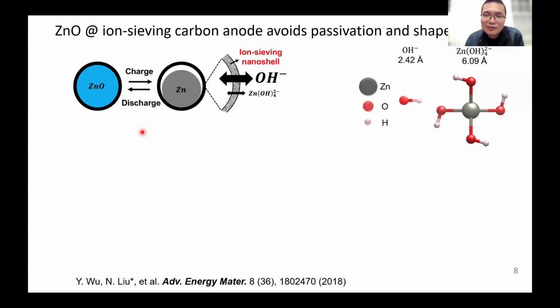Historically, people don't use this type of structure for the zinc electrode, and our approach is very innovative. We hope to use this kind of material innovation to address the historic problem of zinc electrode. The carbon coating has a pore in it. Why do we need a pore? Because we want to block the zincate, but we still want to allow the hydroxide ion to come in and out, because you need that for the reaction to take place.